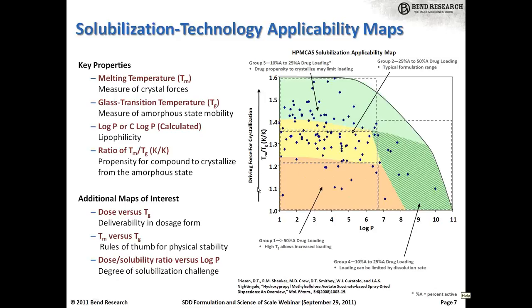The axes on this map are, on the y-axis, the ratio of melting point over glass transition temperature, or Tm over Tg, which is effectively the driving force to crystallize. And then the x-axis is lipophilicity, or log P. So the compounds in here span from, in the upper left-hand corner of the plot, your brick dust, or your very highly crystalline compounds that are difficult to dissolve in anything. Very high melting point, and they do have a strong driving force to crystallize. So the challenge for those, particularly in an amorphous form, is to maintain that amorphous state and prevent recrystallization.